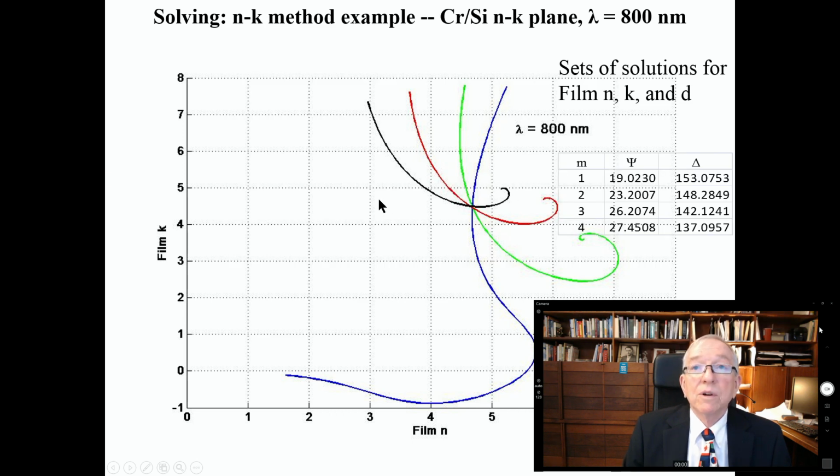And basically what we're saying here is that at any given measurement, and here are the measurements, for measurement number 1, this point here is equally valid a solution as any of the points along this line. And along that line K and N are varying, but D is varying in the Z direction that's poking you in the eye. So every point along there fits with great accuracy the Maxwell equations.